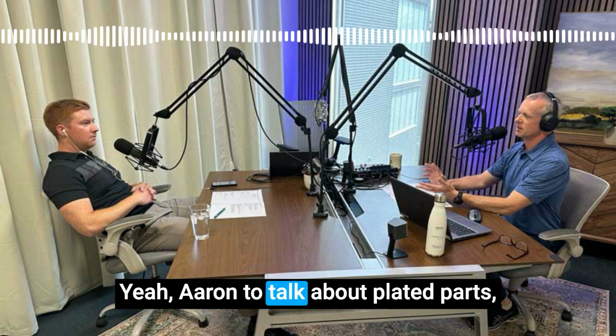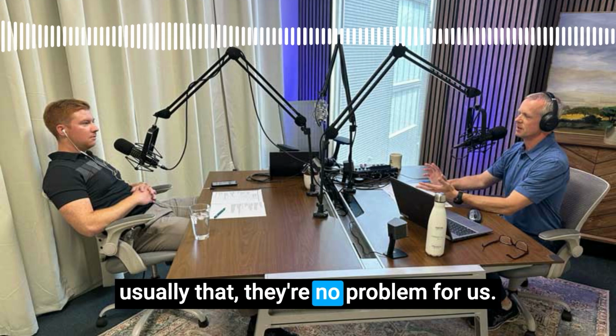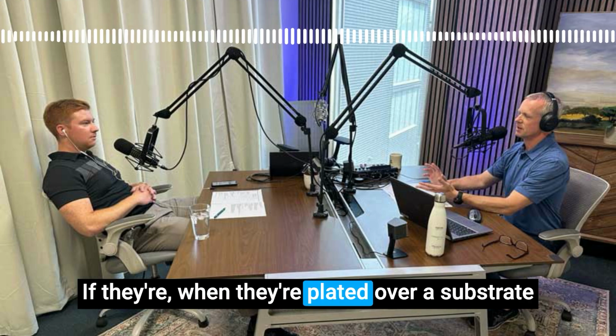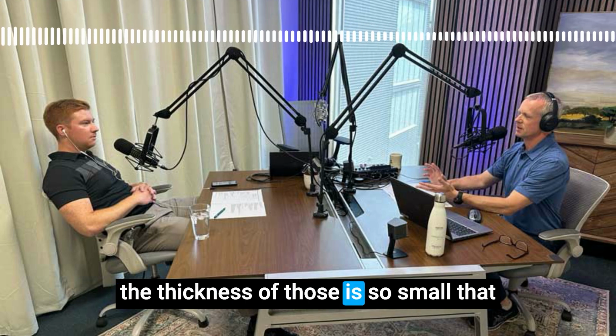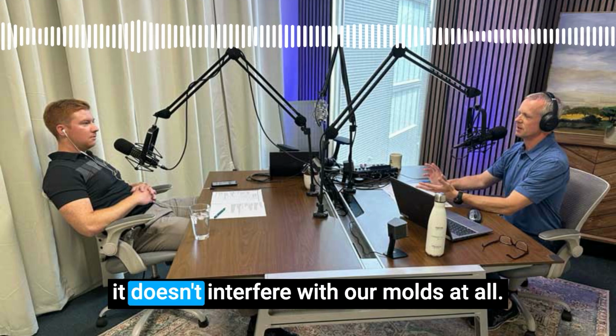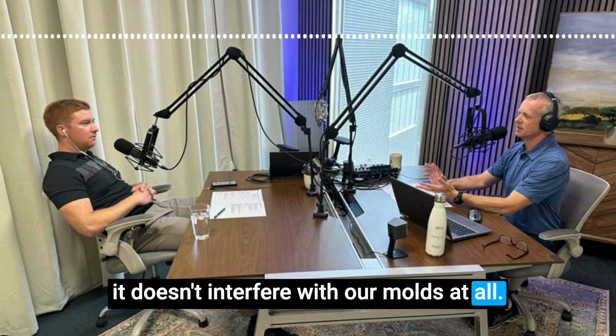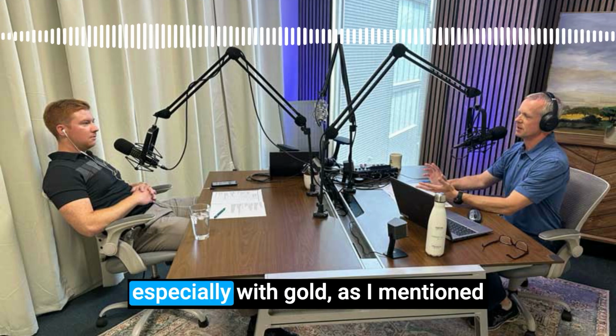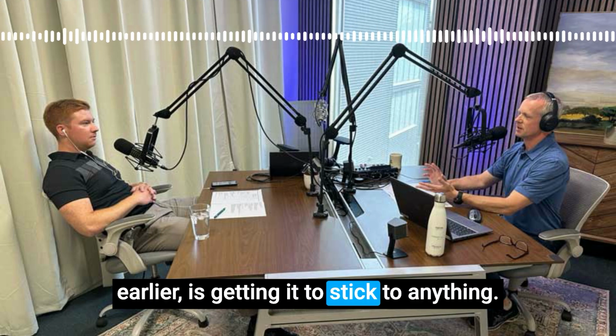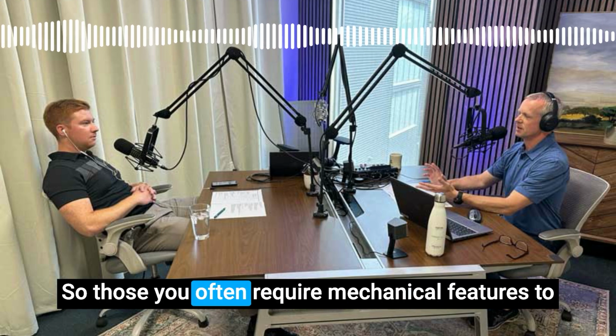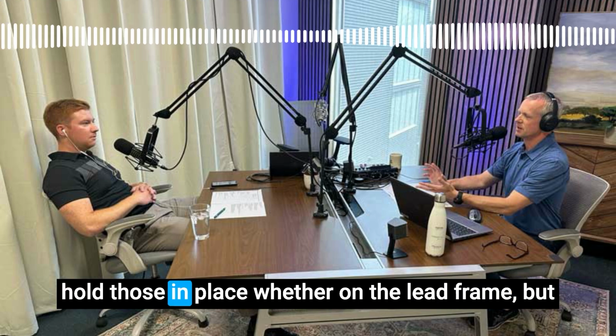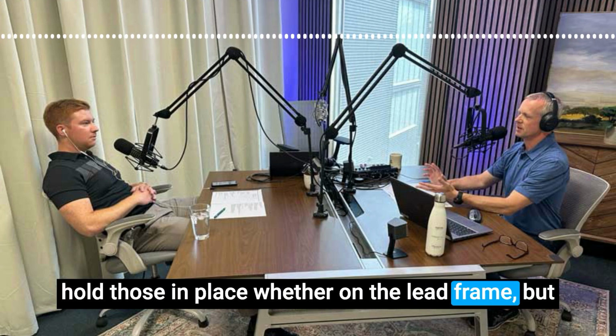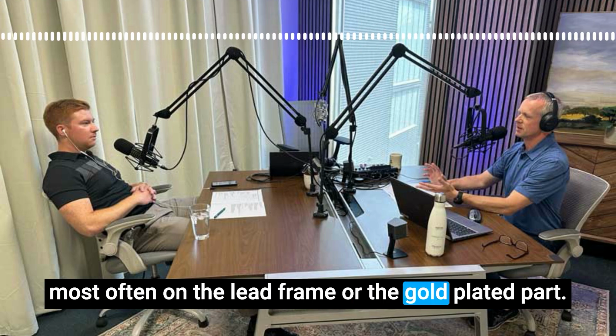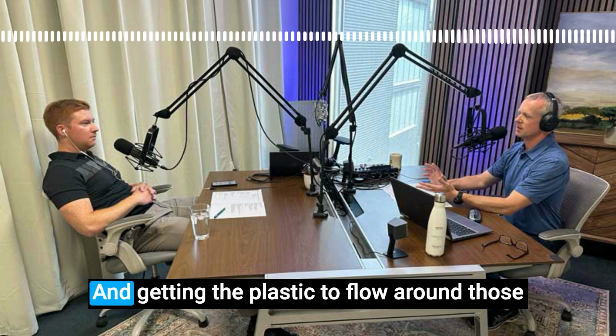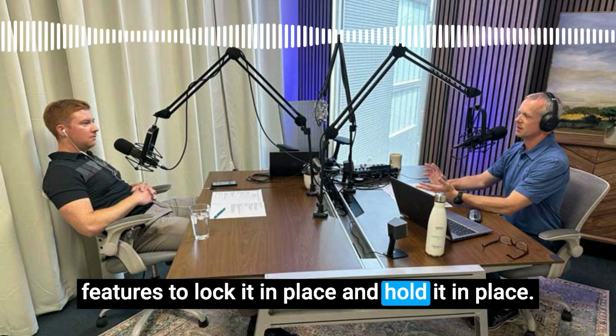Yeah, Aaron, to talk about plated parts, usually they're no problem for us. When they're plated over a substrate, the thickness of those is so small that it doesn't interfere with our molds at all. Usually the problem we run into, especially with gold, as I mentioned earlier, is getting it to stick to anything. So those often require mechanical features to hold them in place, most often on the lead frame or the gold-plated part, and getting the plastic to flow around those features to lock it in place and hold it in place.